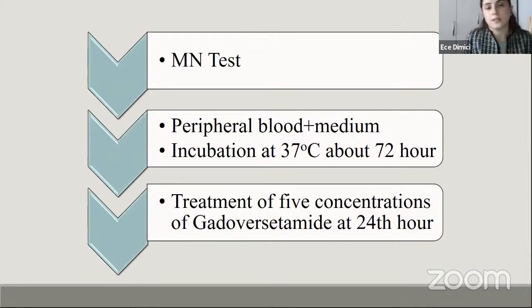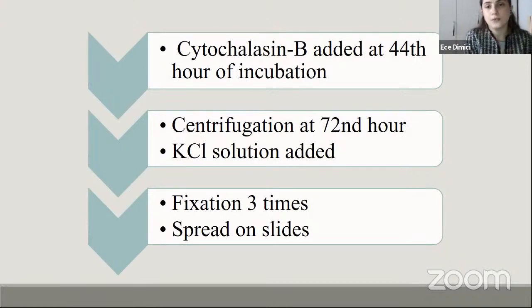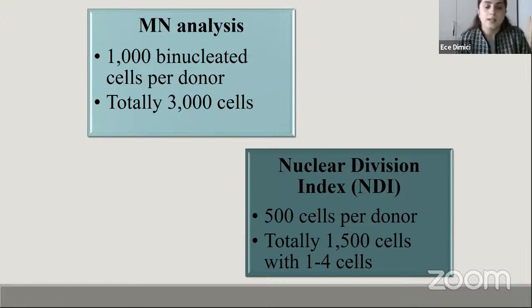The micronucleus test procedure is like this. Firstly, peripheral blood was added to the medium, and this was incubated at 37 degrees Celsius for about 72 hours. The treatment with 5 concentrations of gadoversetamide was performed at the 24th hour of the incubation. After that, at the 44th hour of incubation, cytochalasin B was added to block the cytokinesis of the cell division. At the 72nd hour, the incubation was ended by centrifugation. After that, potassium chloride solution was added as hypotonic solution, and then the cells were fixed 3 times. After that, cells were spread on the slides in order to be analyzed under the microscope.